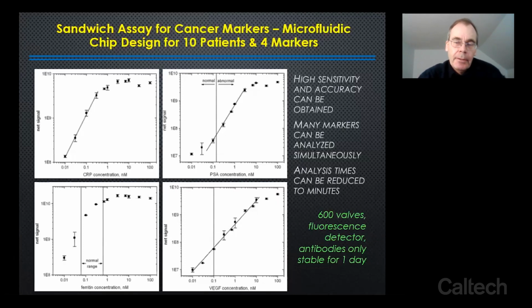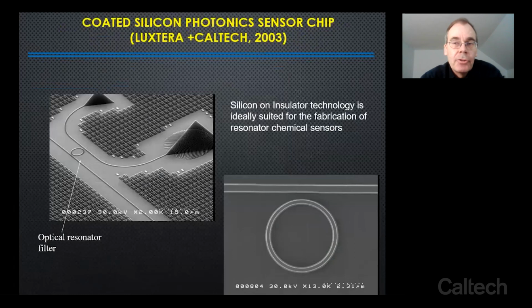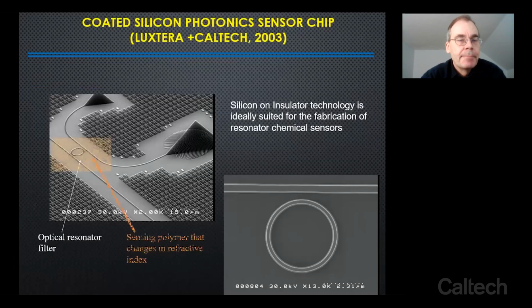And so what we decided to do more recently is to get rid of the fluorescence microscope. And we did that by changing the paradigm of how we measure to measure refractive index changes. So for example, we have a silicon photonics device here. This is an optical resonator that is made on a wafer scale SOI wafer. And it basically allows us to measure the refractive index of its surrounding. So as you have a binding reaction that binds proteins onto this resonator, you change its path length, and you can actually measure how many molecules you bound.